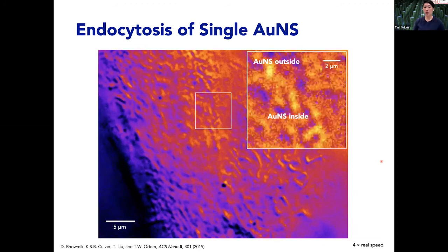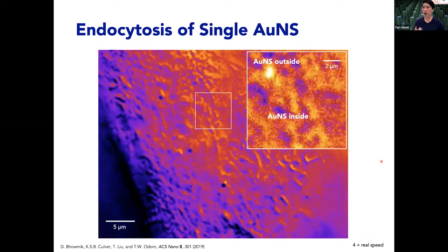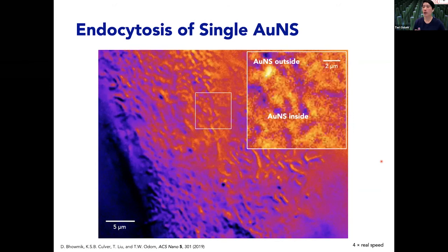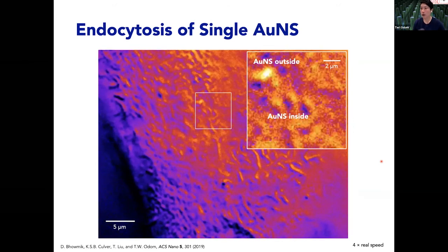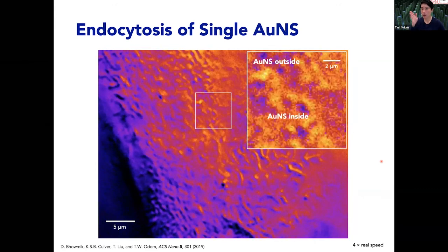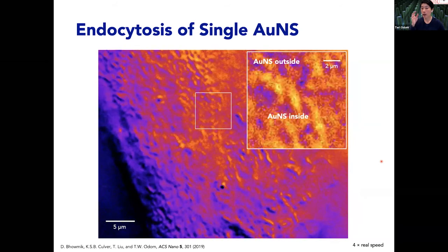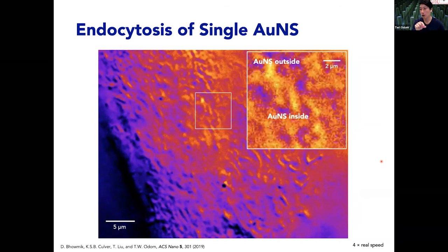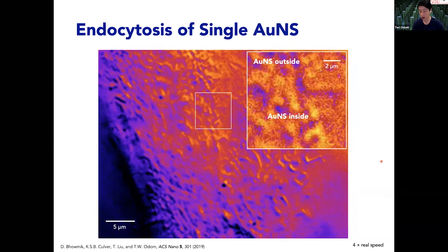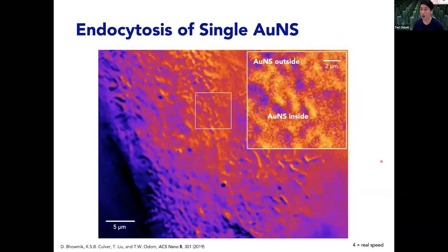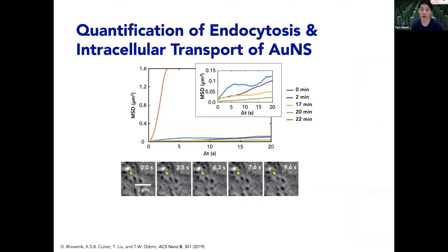So what this means is that once the particle has found the receptor, the particle stops moving. So you can tell this by the rotation. They're not rotating anymore, it just stays fixed. And then after about 10 seconds, it's internalized, and then it translates in a directional way inside the cell. So this is pretty neat. It's one of the first times that we or the community has been able to understand the dynamics of single particle binding, very similar to what you might expect for some viral particle binding.